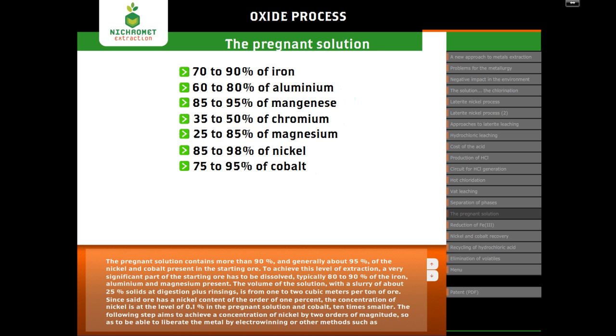The volume of the solution, with a slurry of about 25% solids at digestion plus rinsings, is from 1 to 2 cubic meters per ton of ore. Since said ore has a nickel content of the order of 1%, the concentration of nickel is at the level of 0.1% in the pregnant solution and cobalt, 10 times smaller. The following step aims to achieve a concentration of nickel by 2 orders of magnitude, so as to be able to liberate the metal by electrowinning or other methods such as reduction by hydrogen or deposition via the Mond process.